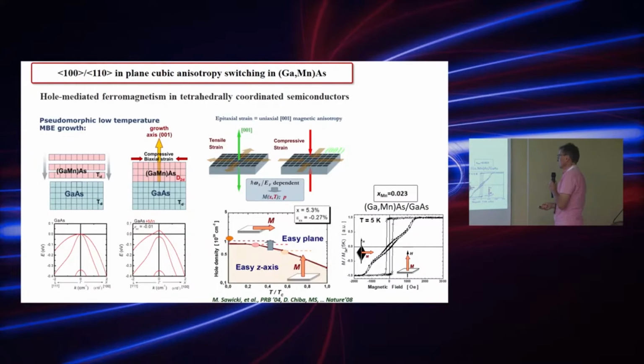And for example, the phase diagram is quite rich because, for the same manganese concentration and the same epitaxial strain, both cases of easy z-axis magnetization, which is perpendicular magnetization, and easy plane magnetization can be realized in exactly the same sample, depending either on the temperature or on the hole density. So, for example, we can switch from easy plane to the perpendicular case by changing the hole concentration, and it has been shown that this is possible. This was published in Nature